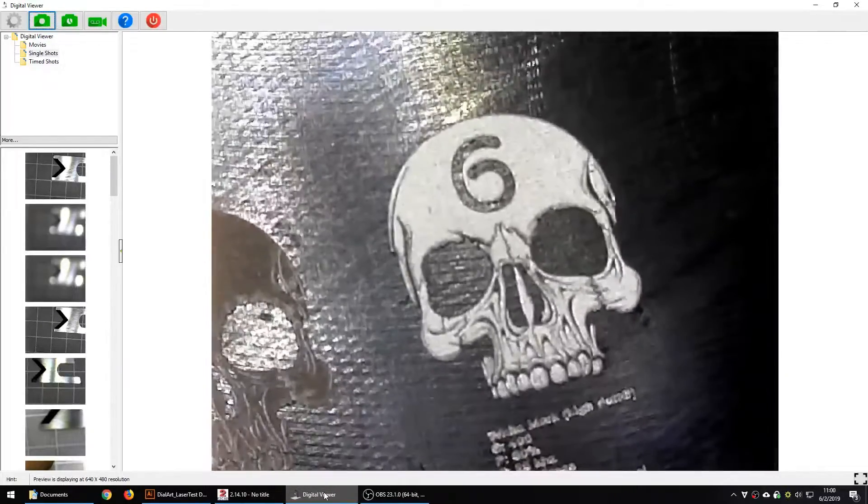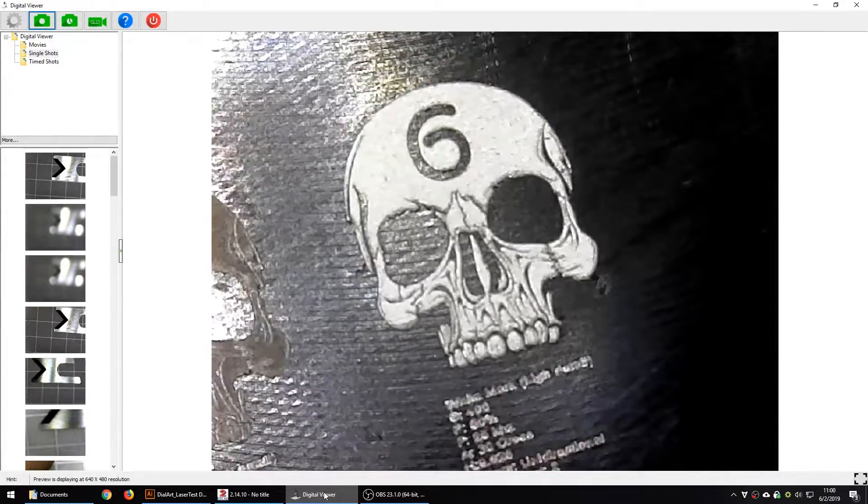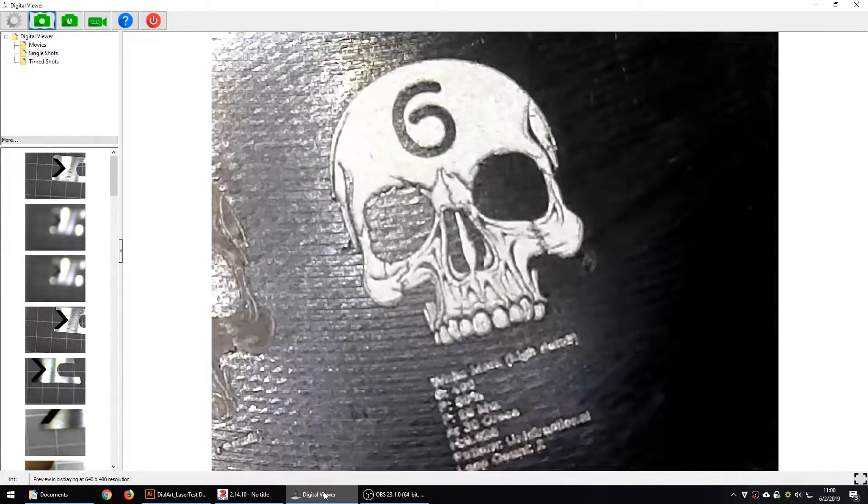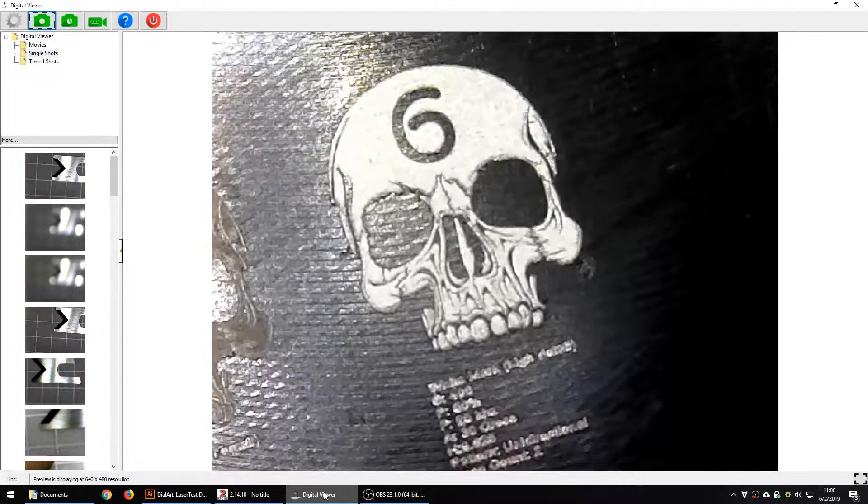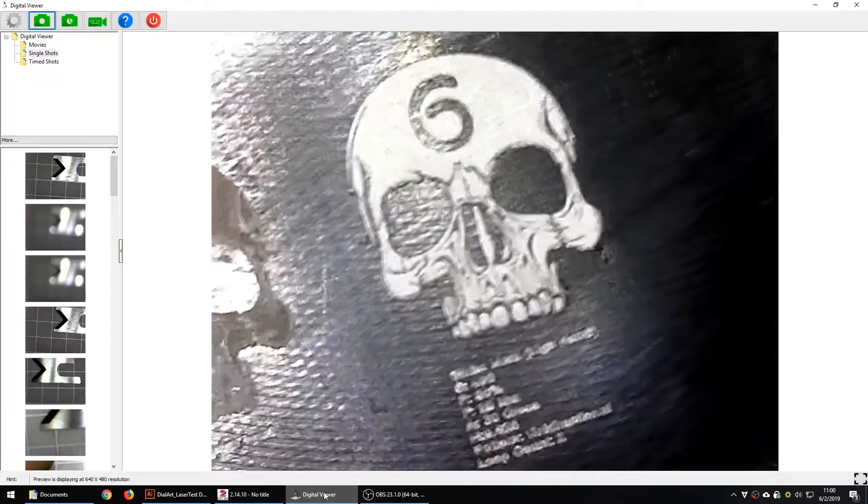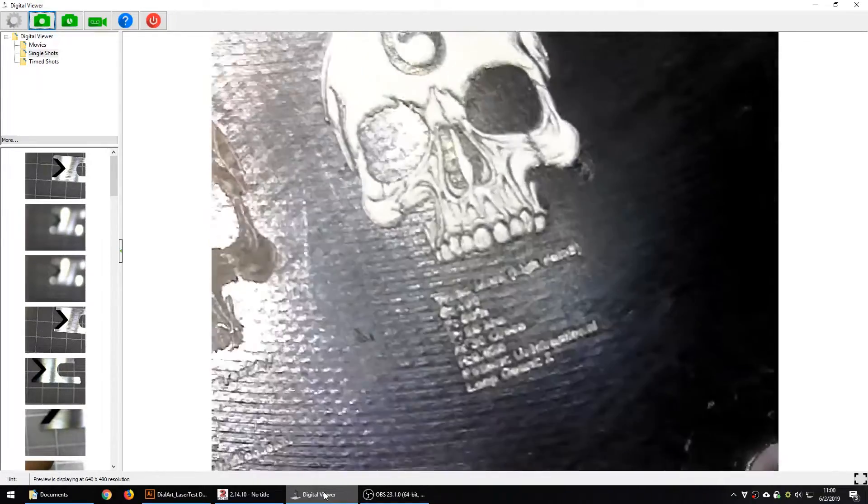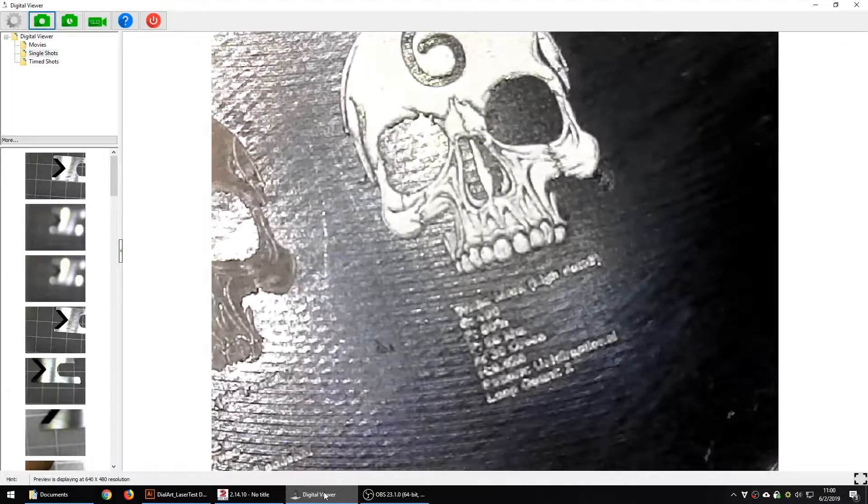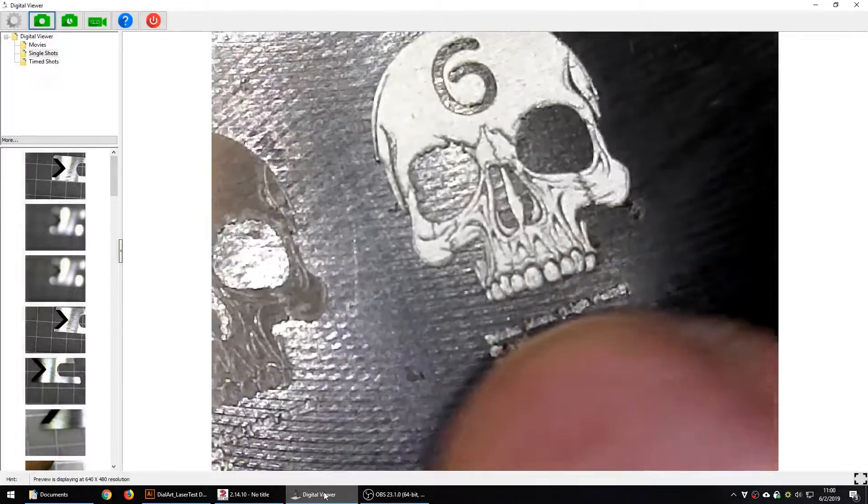This is the one on the right that has 50% power, 400 speed, and this actually has two loops for the pen. Initially I struggled with that because I thought two loops is going to make it worse. If you don't change the direction or the angle and you just repeat the exact same loop you won't lose detail. So you can see I got very good detail in through here, below the eye, above the teeth, around the teeth, and the fractures right between the eyes and even this detail around the nose. It all looks pretty good.